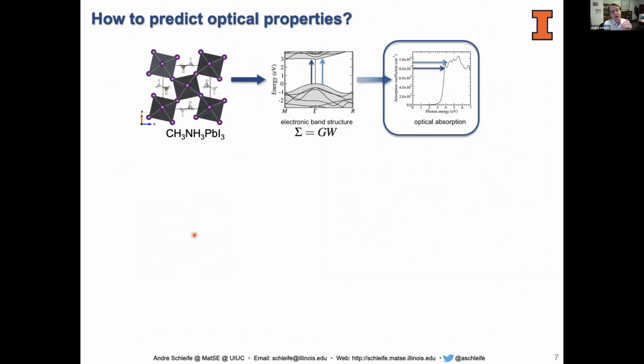So typically when we calculate optical properties, we use a three-step procedure where we first calculate the crystal structure of a material. I'm just using this example here for illustration purposes. You will see one result later on for this material, which is methyl ammonium lead iodide. We obtain the crystal structure from density functional theory, and then we feed that into what is called many-body perturbation theory, in this case within the GW approximation for the self-energy. For those of you in the field, you know this, of course. It's not our technique, it's a standard technique in the literature.